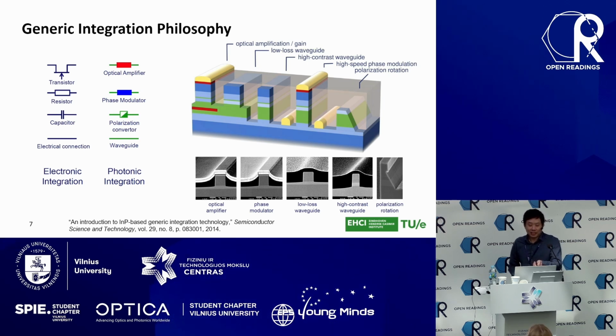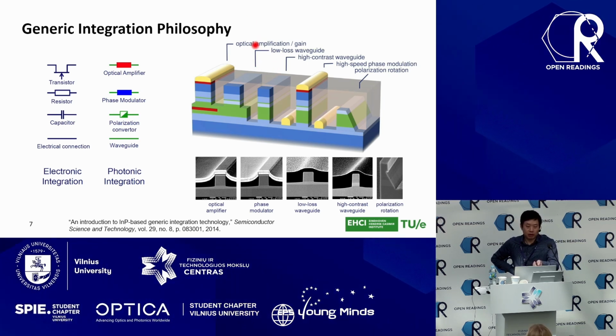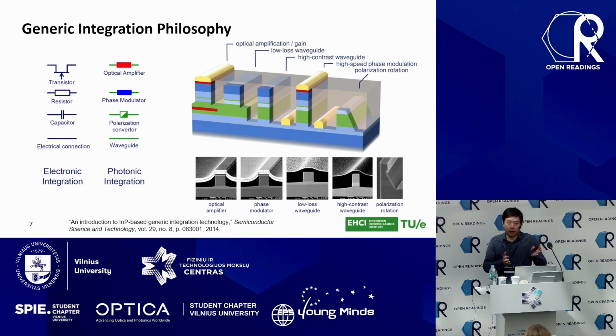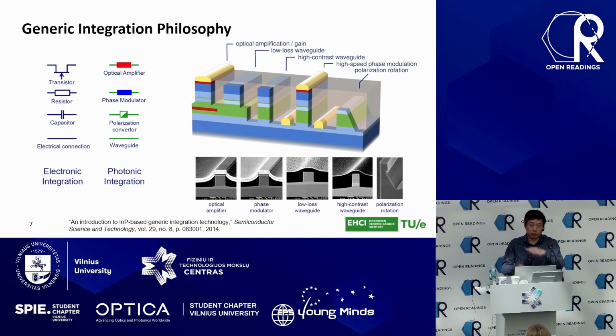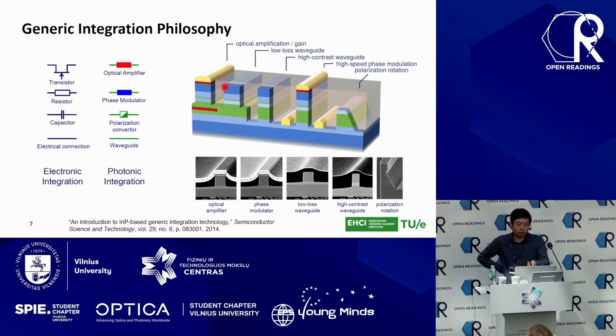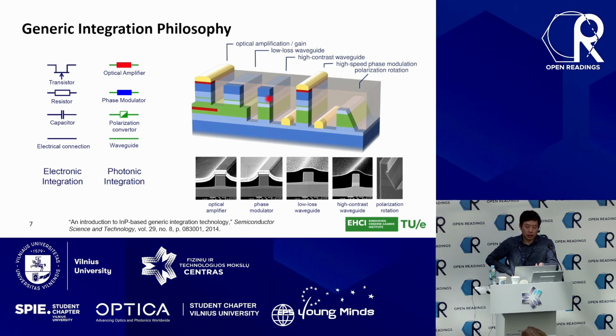You can see that on the same indium phosphide substrate, we can build a complex layer stack, which contains typical anode, cathode, or an active region to form a proper laser diode, which is shown on the left side. And then in the middle, we have a technology to remove the red part, which is the active medium, to make it a passive waveguide, deep, shallow, different optical properties.